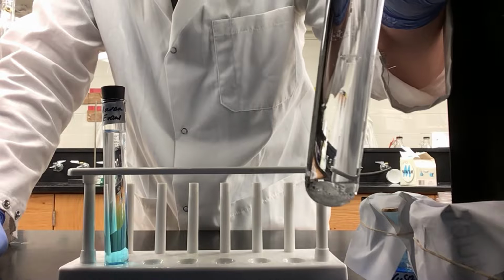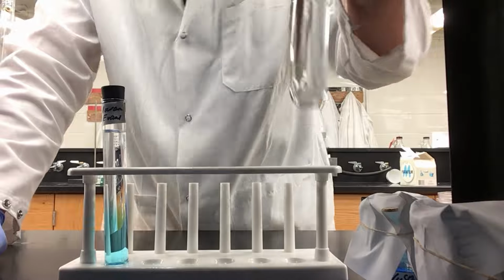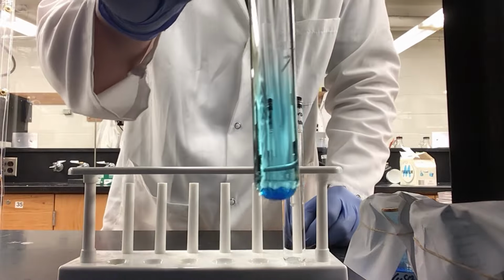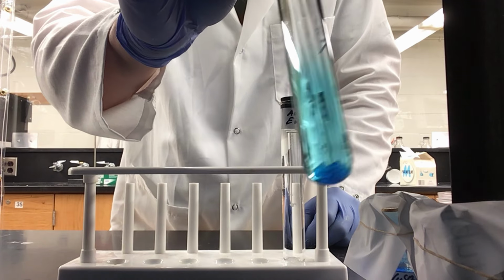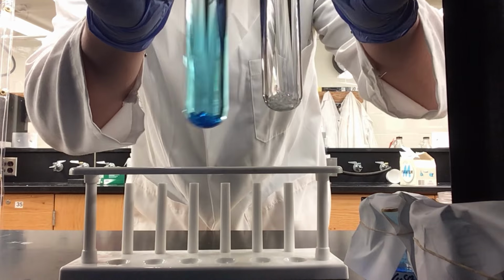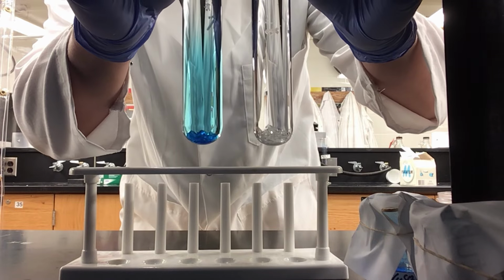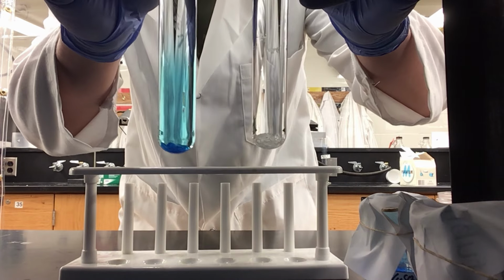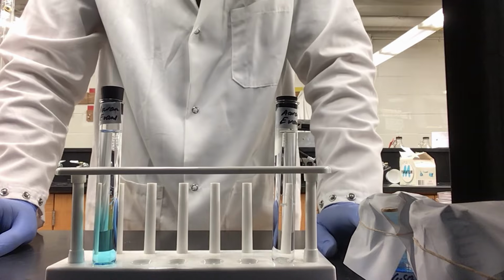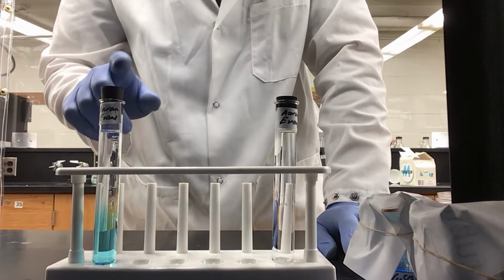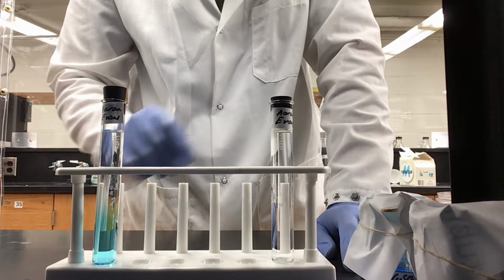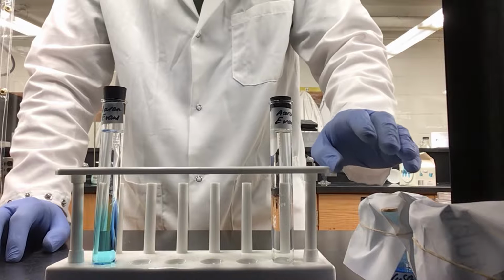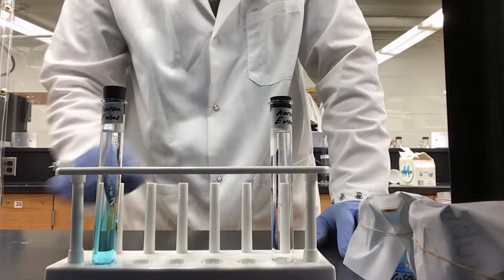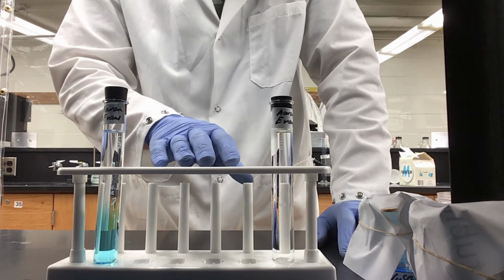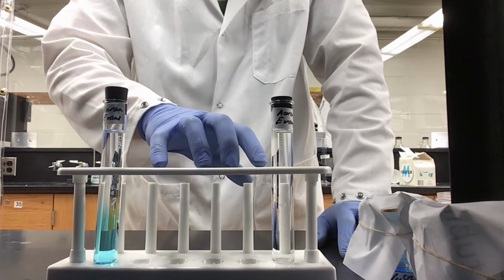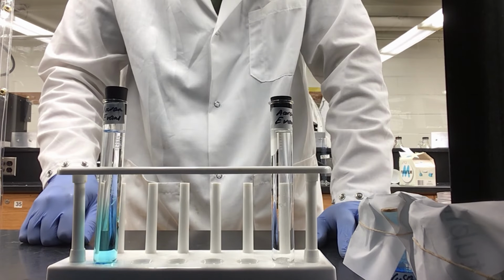As you can see, we have a large amount of growth in our test tube, along with our copper sulfate, which does have some fair amount of growth, but comparing the two of them, you can see that the potassium aluminum sulfate has grown significantly more crystals than the copper sulfate. And as you saw with our slow evaporation, our copper sulfate had many, many more crystals than our potassium aluminum sulfate did in our slow evaporation. So as you can see, the two different methods grow crystals in a different way, and they work better for different material. You can go ahead and make a hypothesis as to why which method works better for which material.